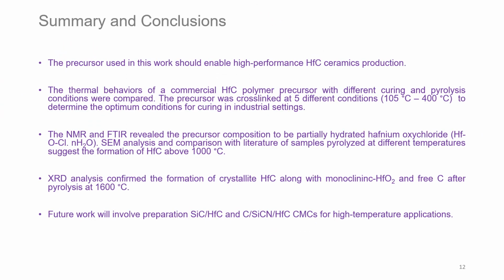To summarize and conclude my presentation today, we have used a commercial hafnium carbide precursor to determine its thermal behavior at different curing and pyrolysis temperatures. The NMR and FTIR characterizations were utilized to determine the precursor's composition, which is hydrated hafnium oxychloride. SEM micrographs suggested that the hafnium carbide crystals start to appear above 1000 degrees centigrade. The XRD analysis confirmed the presence of hafnium carbide along with monoclinic hafnia and free carbon in the pyrolyzed structures. Future work involves the fabrication and high temperature testing of this multi-layered, multi-phase hafnium carbide silicon carbide ceramic matrix composite.